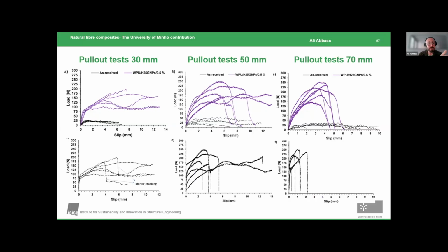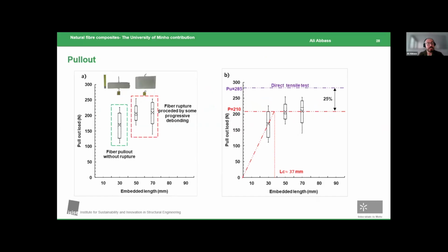You can understand better what's going on here when you see the displacement at the free end. You would see the free end displacement starts to happen when we have full friction achieved. And you will see here that you have slip hardening after friction is going on. This means friction is stronger than the adhesion itself, and we have mechanical interlocking dictating the interface rather than adhesion. Based on this, we evaluated the effective bond length based on the best-fit graphical estimation. It was around 37 millimeters.